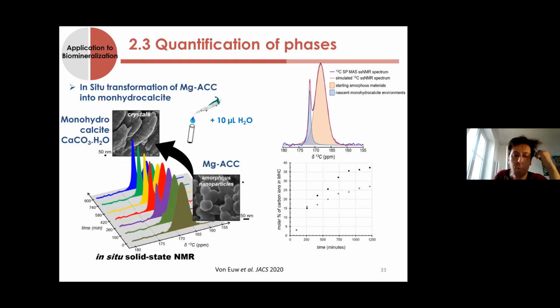You can also monitor the transformation of some amorphous calcium carbonate phase into a crystalline one. And here is the monitoring of amorphous calcium carbonate. You see that with time, you have a very thin line width that is increasing, as you can see here. This is the decomposition, and then you can have the relative proportion of the two phases also.